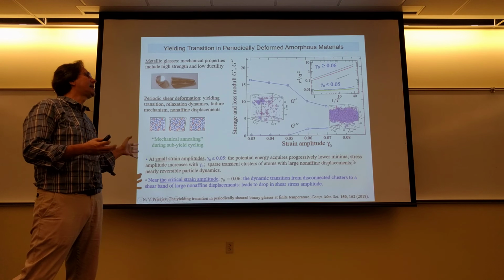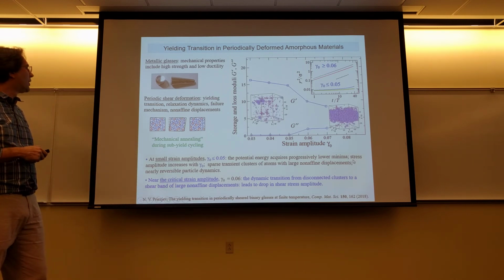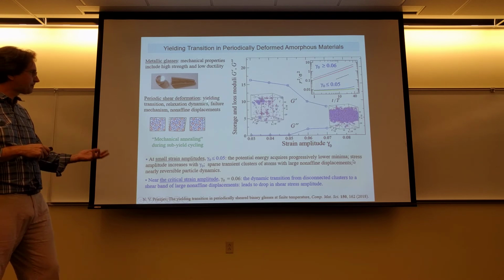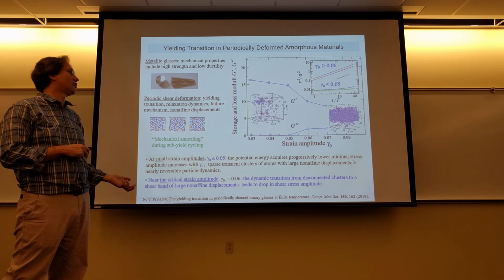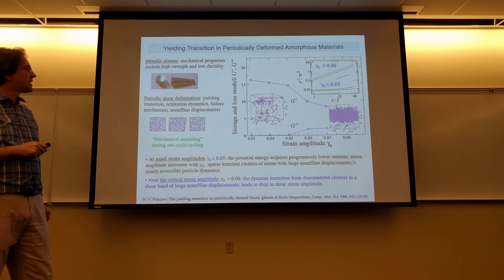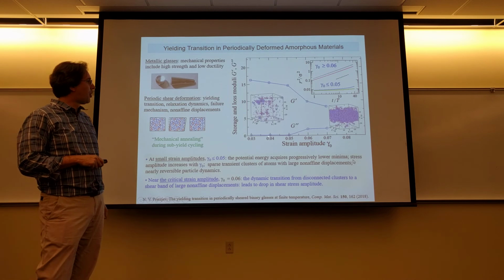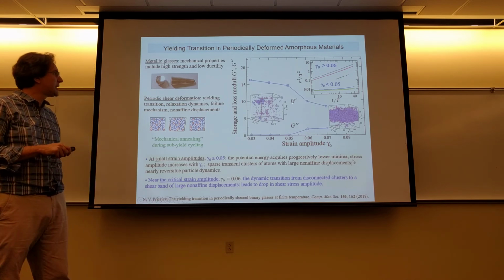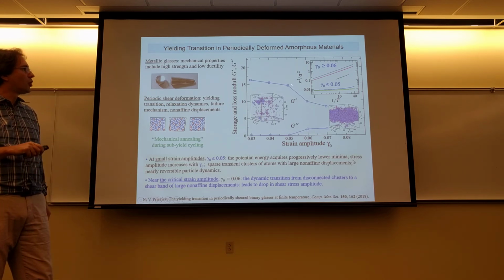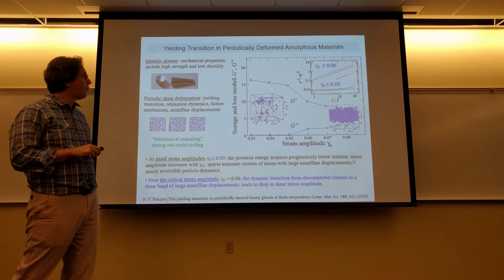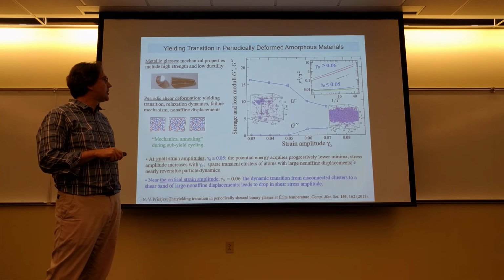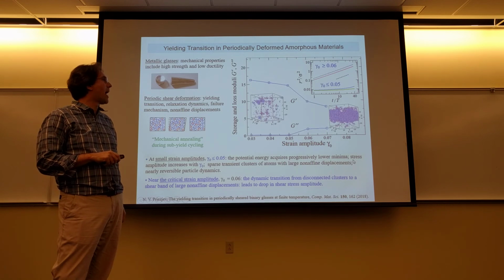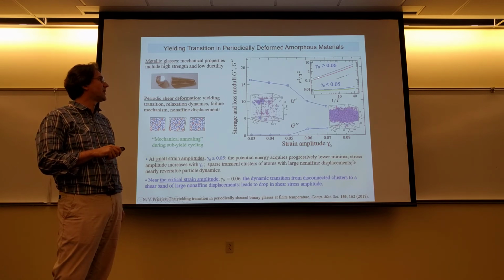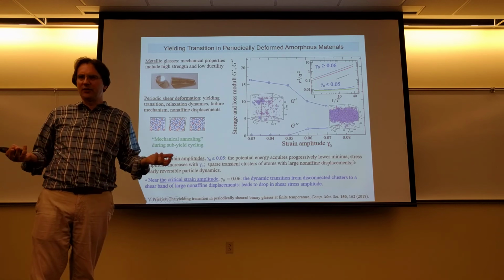What we can see here is one example where one can apply periodic shear deformation and see the structural relaxation of the material. These results can be summarized in this plot where we have mechanical response versus strain amplitude, and what we see here is that at low amplitude loading we have an elastic regime followed by yielding, which is associated with a shear band, and atoms within the shear band will pick up diffusive motion.